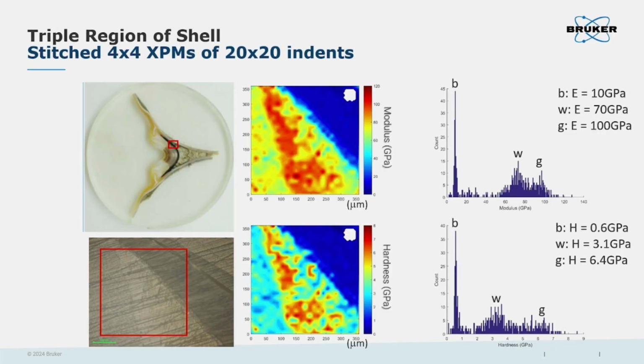And then we can go to another interesting region. Again, we select this region because we can see three different colors in this region via the optical microscope. So we have this one, and this one. We can make, again, 400 indentations in a 20 by 20 array. Then this is the modulus map, this is the hardness map. Again, we have the medial region which has the higher modulus and the higher hardness.